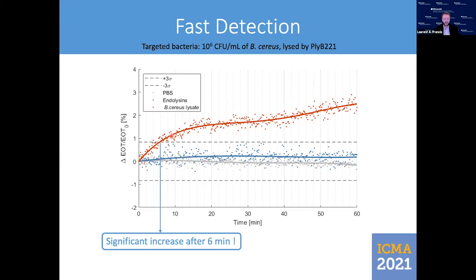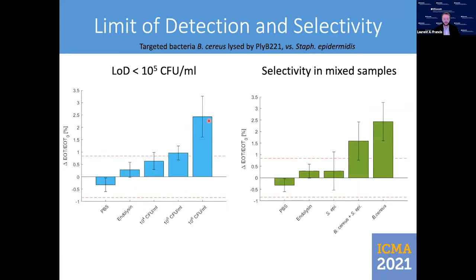Finally, in red, when using the bacterial lysate as an analyte, the effective optical thickness increases quickly, reaching the noise level after a few minutes, and the average total increase after 1 hour was calculated up to 2.35%. As mentioned before, 1 milliliter of bacterial lysate was used for this detection, indicating that we can detect the lysate for this huge concentration, 10 to the power 6 units per milliliter, in less than 10 minutes.